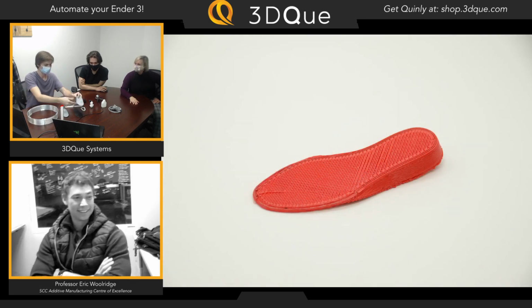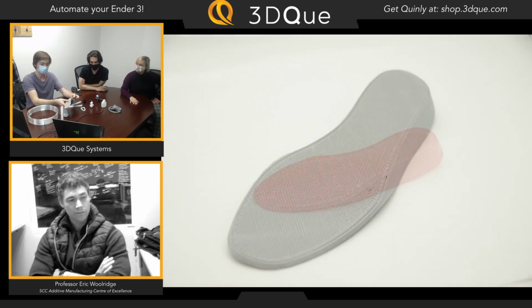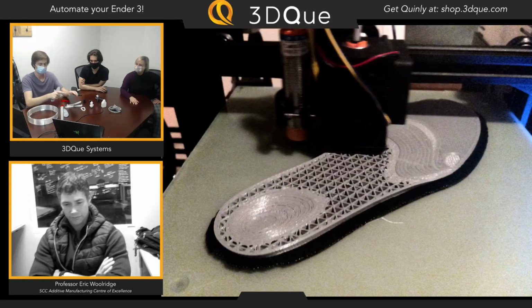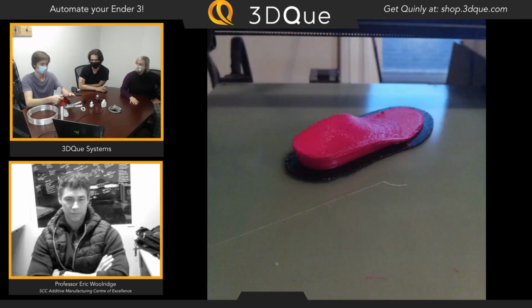So the method I came up with is essentially just printing a raft out of PLA. Everyone knows what a raft is. It's something that you print the first few layers with so that it cancels out any unevenness on your build plate, and it also gives you a really nice smooth printing surface to start with. But the thing with PLA is that it releases really well from our build plates, unlike TPU.